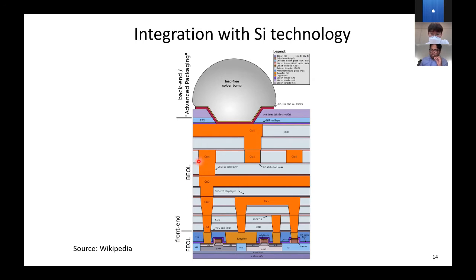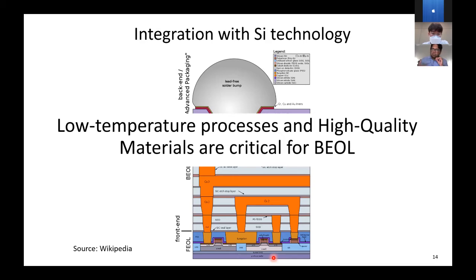The problem is, once you make front end of the line, there is a thermal budget assigned. The thermal budget is about 400 degrees Celsius. So you want to make the back end of the line layers within 400 degrees Celsius thermal budget. Otherwise, your front end will get destroyed and it is pointless, right? So the key to making back end of the line integration of memory devices or MEMS devices or photonic devices is that you need low temperature processes. At the same time, you need high quality materials at low temperature processes. This is hard to achieve. This is thermodynamically a huge challenge for material science, right? A lot of times material science want high quality materials, but they have to go to high temperatures for that.